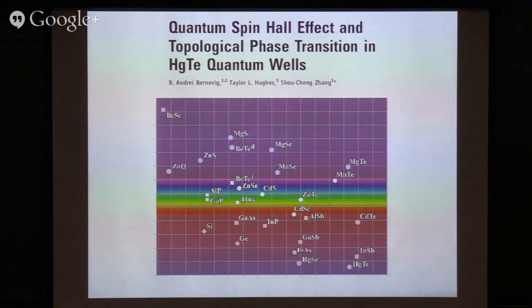And so that's very useful. On the horizontal axis, people usually plot the lattice constant, and then people can put heterojunctions together because they're more or less lattice matched, so they know they can construct interesting material by stacking them on top of each other. But one day, as we were staring at this graph, we suddenly noticed there's something very, very strange about these plots. That actually there's absolute zero for the energy gap.